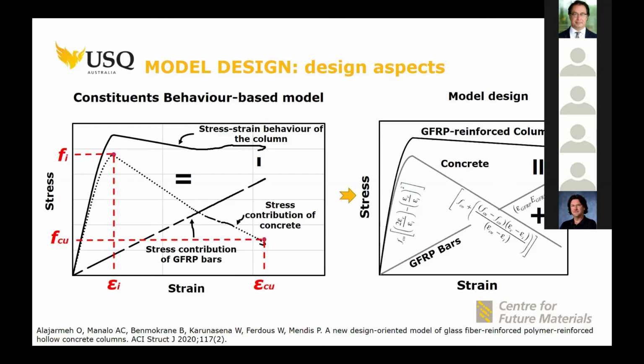Exactly. So our study actually was after my PhD, but it's related to that. It's more about measuring not the tensile failure, but the strain failure of the bars. And that was quite similar to what we got from the test results of testing these bars alone. It was around 70% compared to the tensile strain failure.